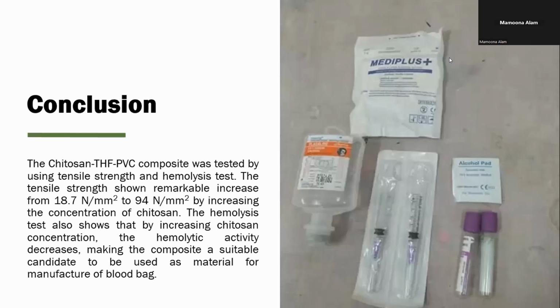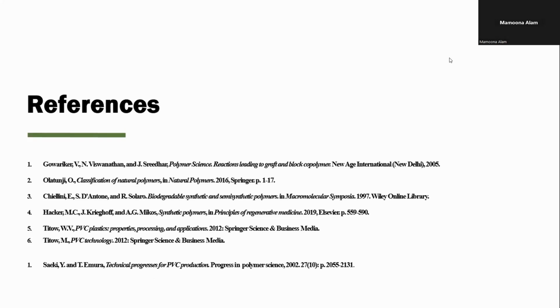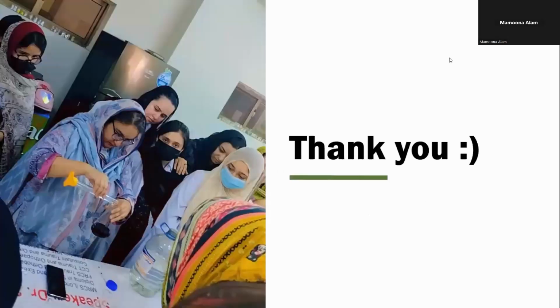The conclusion is that the chitosan THF PVC composite was tested using the tensile strength and hemolytic tests. As I said, the 1:1 ratio membrane was the best, giving me 94% strength. At the same time, it is also blood friendly, and chitosan has the property of antimicrobial activity, which is very helpful for the shelf life of blood storage in blood bags. After this study, we recommend chitosan PVC based blood bags for longer shelf life of blood in blood banks. These were the references I used in my study, and thank you so much.